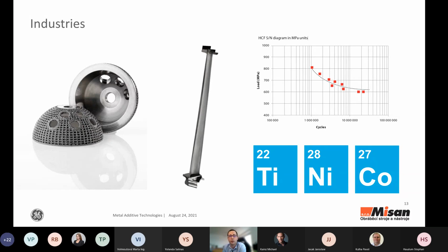Another big advantage here, apart from the productivity, is that you can produce parts that have very good fatigue properties. They can also work with higher temperatures. That's why the turbine is here. So these are the parts that you can spin up, and they will do just fine. The properties are usually higher than you would get with forging. So if you apply hot isostatic pressing afterwards, then you're really able to increase the toughness of this part to the maximum.